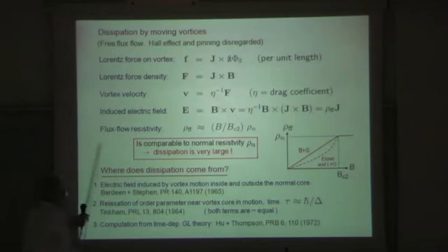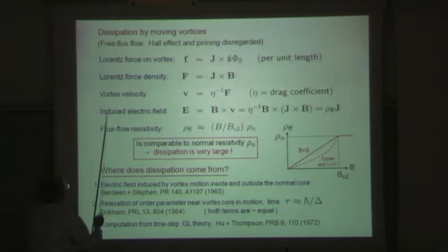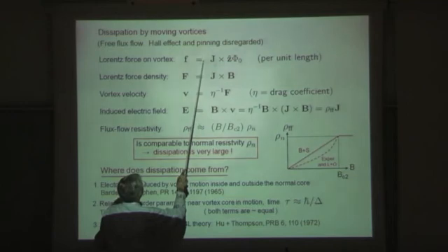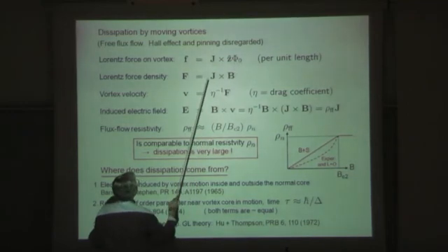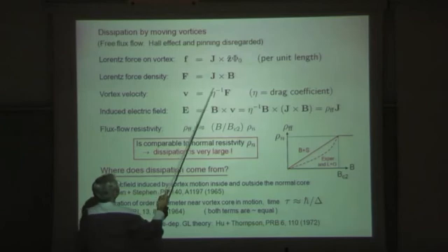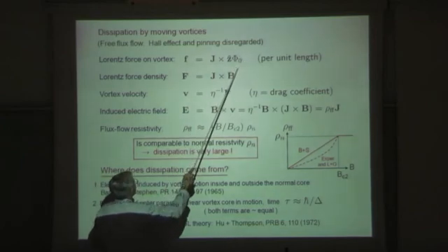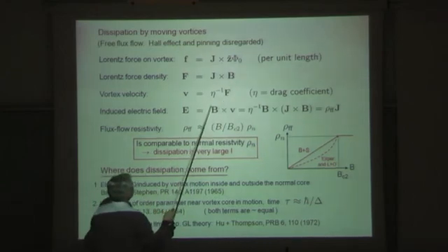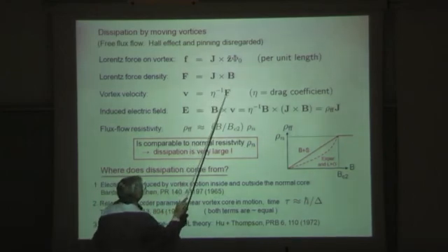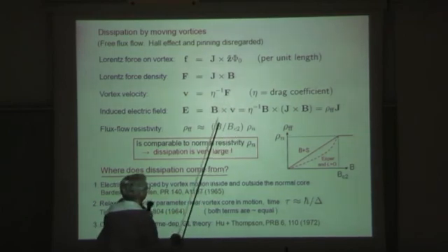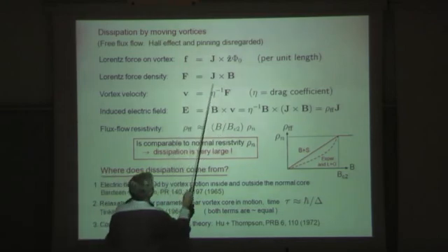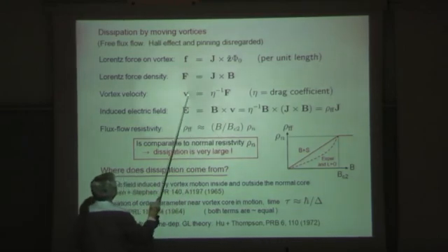Now, I come to the next point. I don't have much time left. The dissipation by moving vortices. So, a Lorentz force on vortices when you apply a current. And this is a force on one vortex. And the Lorentz force density is the same, but times the density of vortices. So, the phi zero becomes B, the induction. And the velocity is then assumed to be just proportional to the force. So, it's so-called drag coefficient, or it's also called viscosity. It's not a real viscosity. It's just the coefficient of proportionality between...